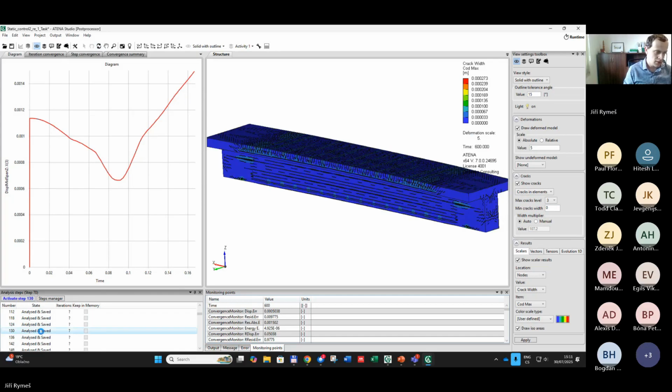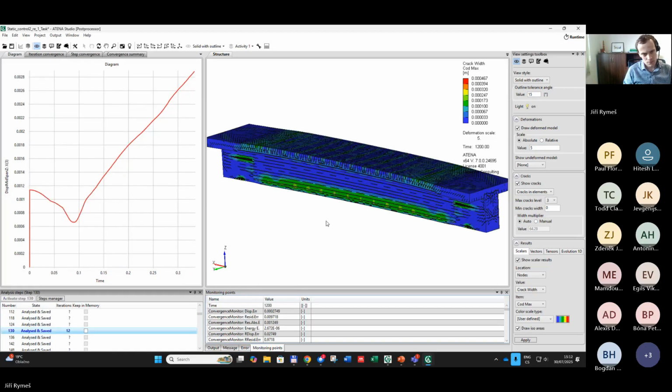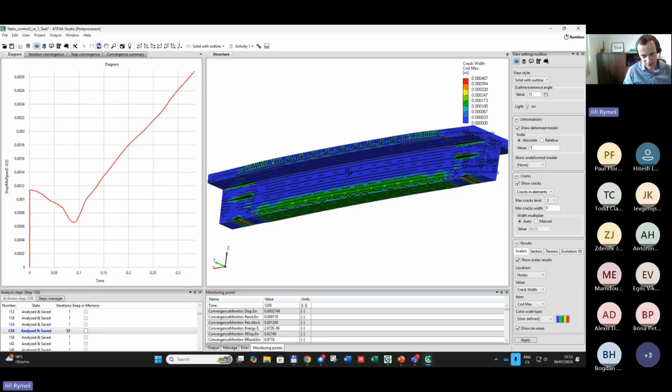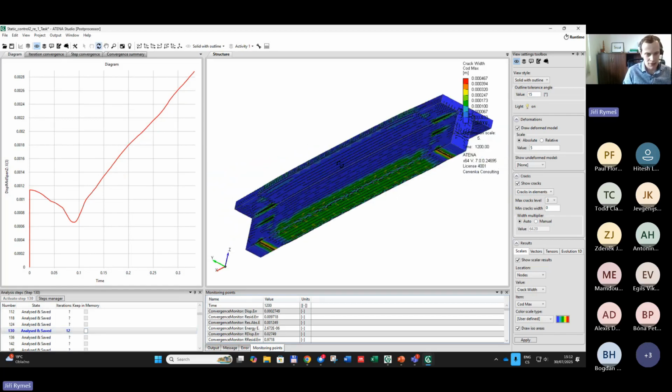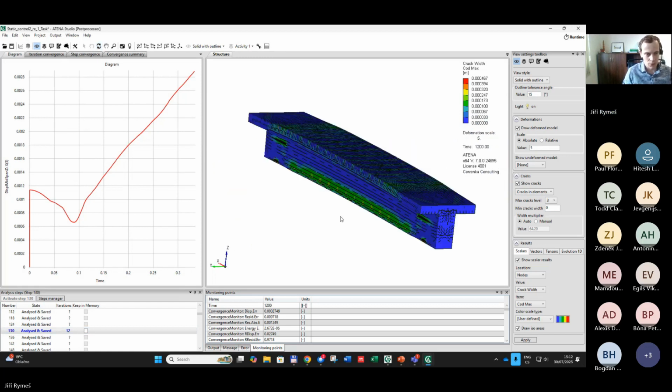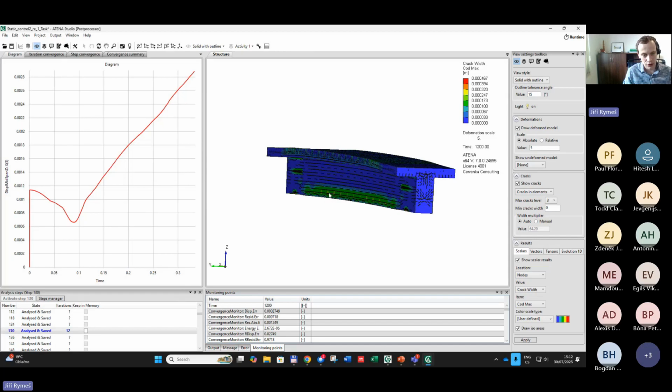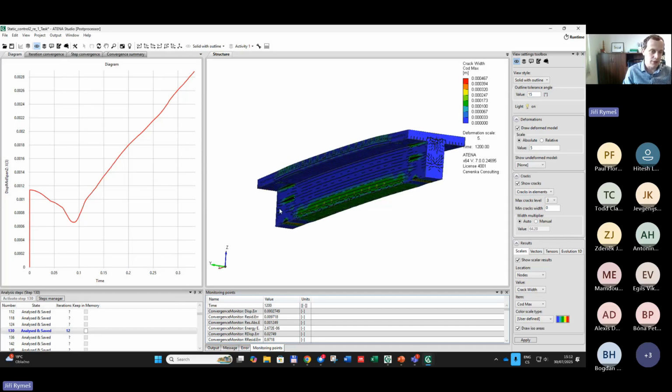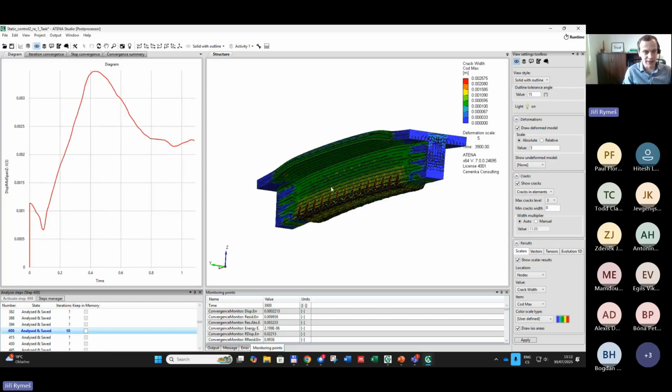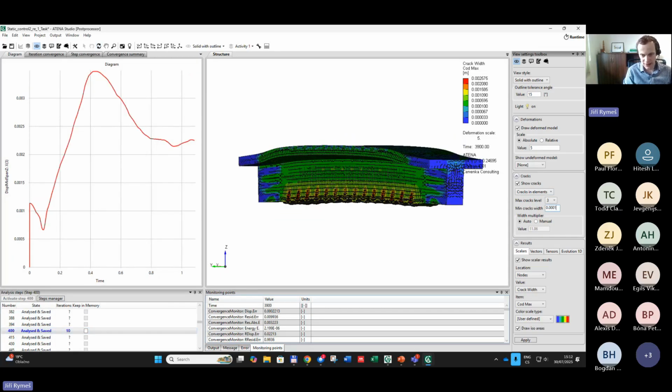After 20 minutes, you can see that this area at the bottom, actually the cover distance from the reinforcement, starts to crack, and then at the end of the fire, at the moment of the maximum temperature, these cracks grow significantly. Again, I will now apply the filter.